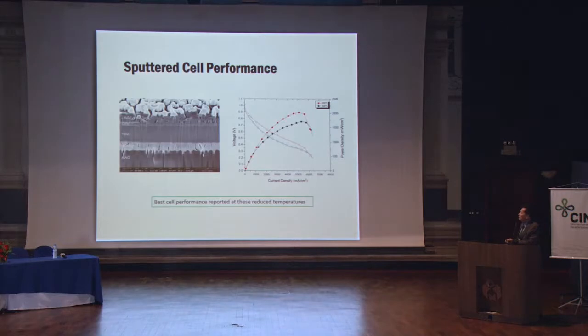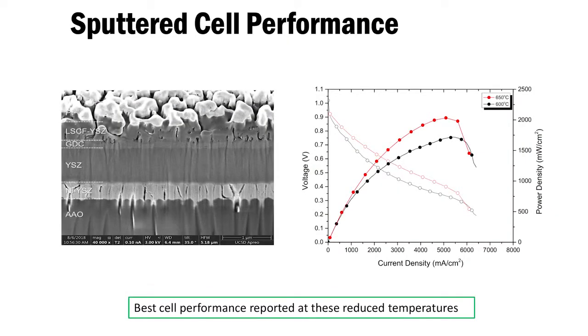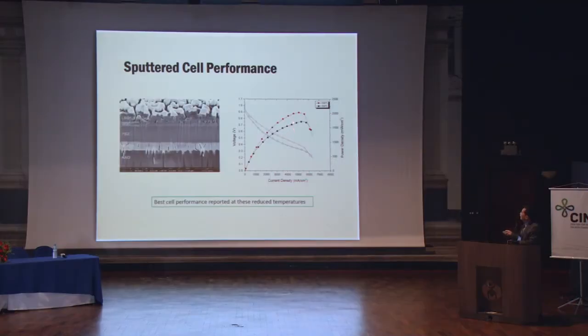Here is an example of the performance of the thin film we deposited on the AAO. This is the microstructure of the cell, and this is the performance at 650 and 600 degrees C, and you can see that we demonstrate about 2 watts per square centimeter at 650 and about 1.7 watts per square centimeter at 600 degrees C. And to my knowledge, that's the best cell performance at this temperature for SOFC.